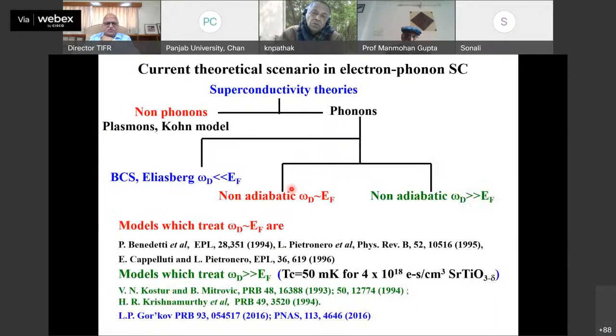That's what we are trying to do recently. So now, once we have established the superconductivity, let's look at some of the theories. Superconducting theories can be classified as phonons, non-phonons. Then you have for phonons this Eliashberg theory, which tells you the superconductivity of transition metals which have large electron-phonon coupling constants. The phonons can be adiabatic or non-adiabatic.